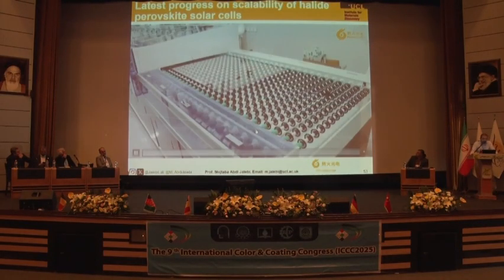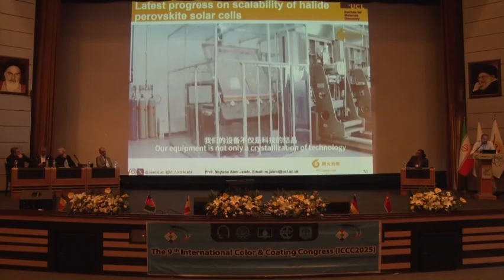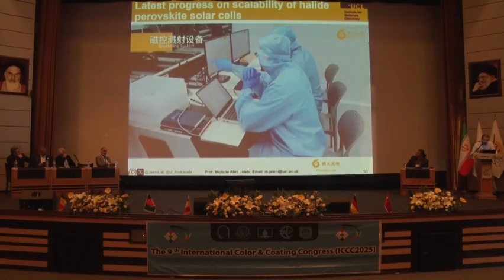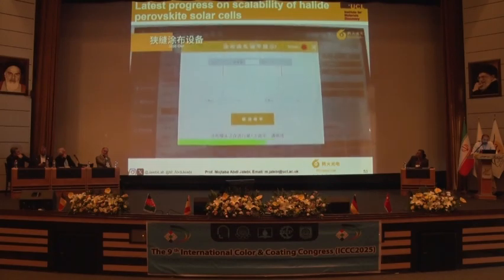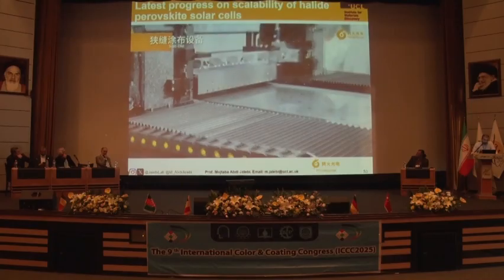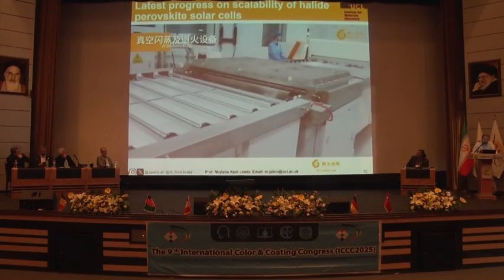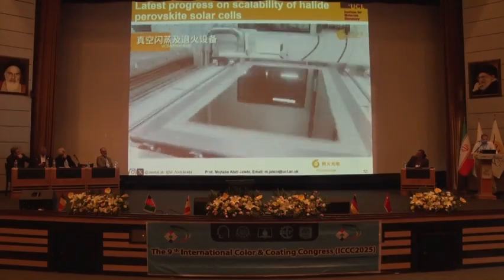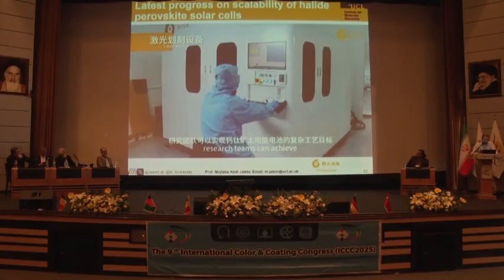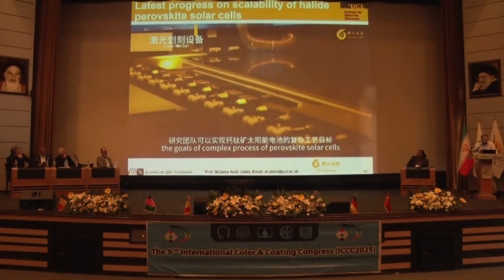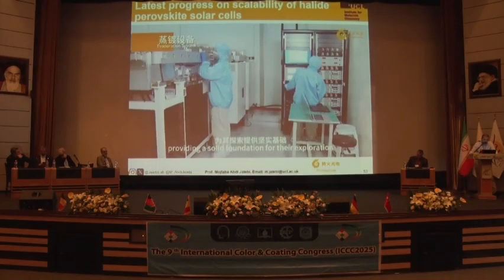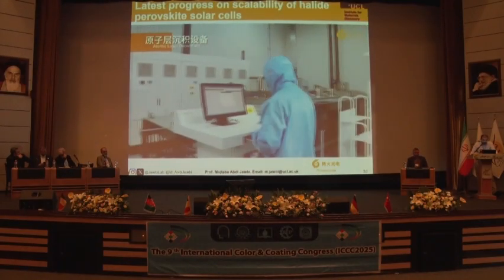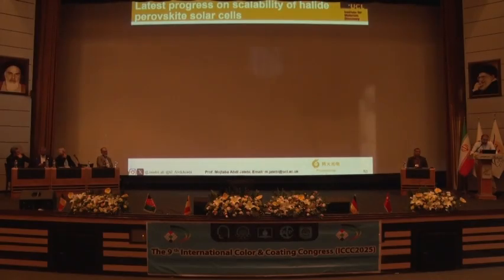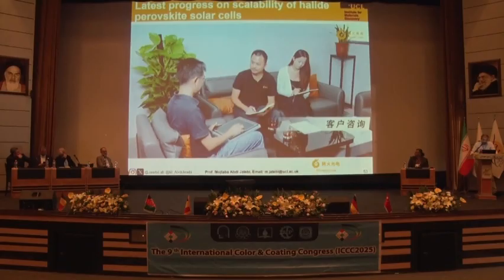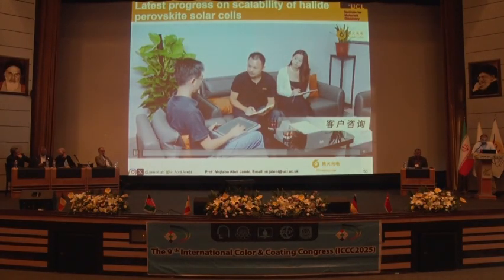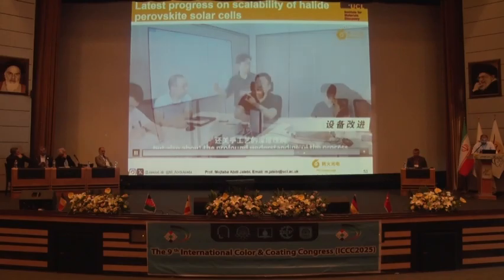Right, so this is the starting point where you start with a transparent conductive oxide coated glass. Then you put it in the machine for sputtering to make the ETL layer. Once you deposit your electron transport layer, you go to the slot die machine, as you can see over here, where you deposit your perovskite absorber layer. Then you anneal the perovskite using the VCD technique, vacuum, and then you do the scribing to make small sub-panels, and then an evaporation system to do the other layers, the HTL and the contact layer. And finally, atomic layer deposition to finish the cell. And obviously, afterwards, you go to characterization to see the performance of your cells.